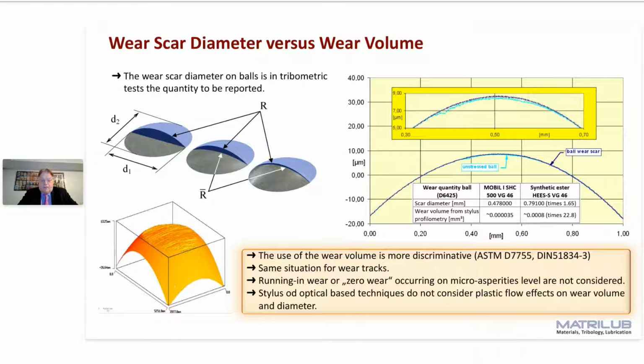To give you some figures, in a test according to D6425, you have 2 different lubricants. One has a wear scar diameter of 0.478, the other one of 0.79. This is 1.65 times higher for the synthetic ester. But if you determine the wear volume, you have a difference of close to 23. This is why it is really better, but a little bit more complicated, that you determine on all specimens the wear volume, because you can much better discriminate or differentiate between additives, lubricants, and also materials.